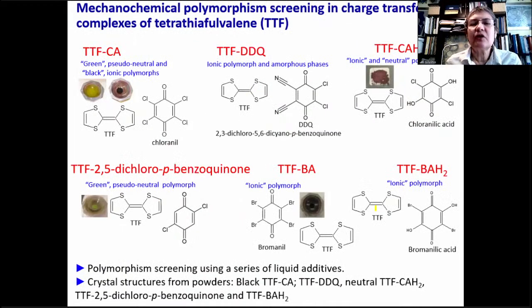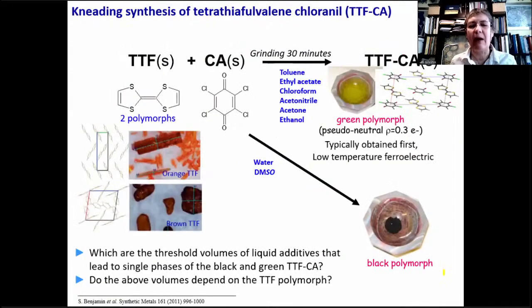So I have studied various of these systems, which are shown there. I have done mostly a polymorphism screening using a series of liquid additives, leading to different polymorphs of the charge transfer products. And I will talk about the two most interesting, which are tetrathiafulvalene chloranil, that forms these two green and black polymorphs, and tetrathiafulvalene chloranilic acid, which forms these two other polymorphs, which in this case have the same color. And the use of liquid additives was necessary to prepare single phases of the different polymorphs that were used in various cases for crystal structure solution from powders.